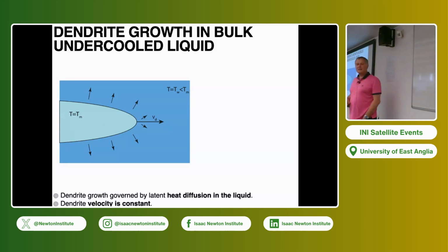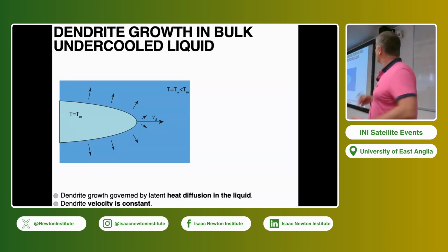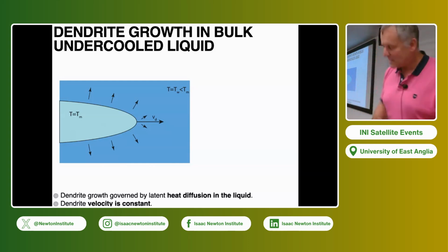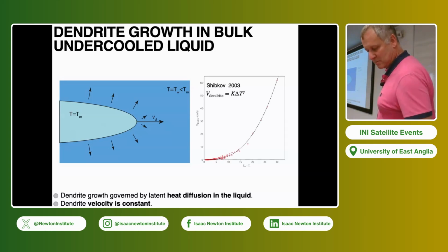And again, there are some analytical solutions of that, and actually there was a lot of analytical work in the 80s about that. They found that it's something very similar to the Saffman-Taylor instability, in the sense that for the velocity of the dendrite as a function of the undercooling, there is an infinite number of solutions if you neglect the surface tension. The one that is selected by surface tension makes the relation between the velocity and the undercooling. So again, like Saffman-Taylor, there is an infinite number of solutions, and the one which is selected is due to the surface tension.